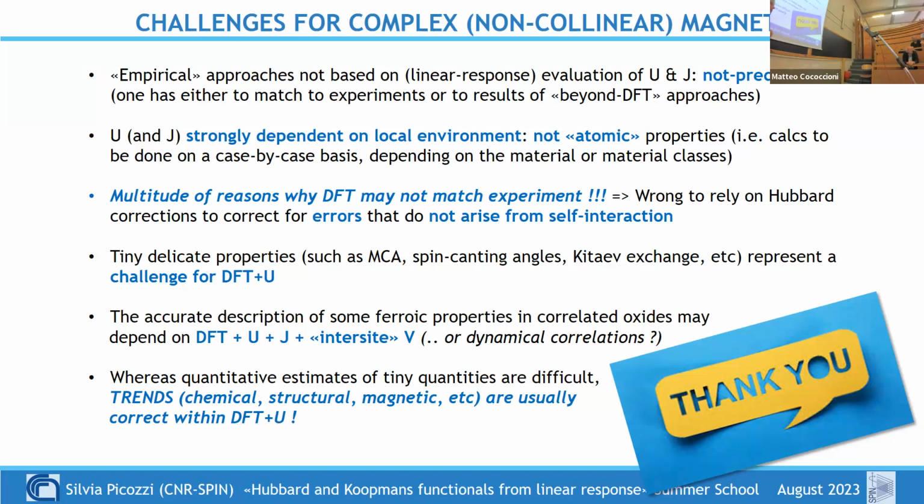This approximation is not rigorously true, but in practice your spin is still localized, and you can still use it, although not rigorously. Maybe that's also true depending on the system. If you take an oxide, like a five-d magnet, your spin is localized, and it goes metallic, but then your screening is strong, and your interactions are still short range. So I would say that although not rigorously, you can still use it. But whether rigorously you can evaluate J consistently, this probably is not true.